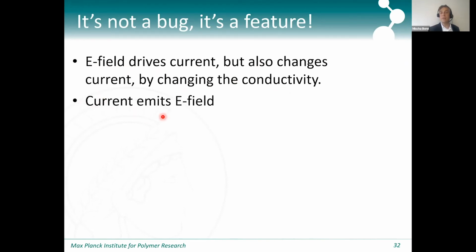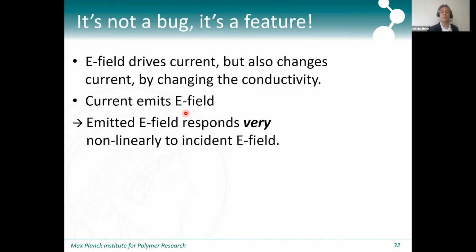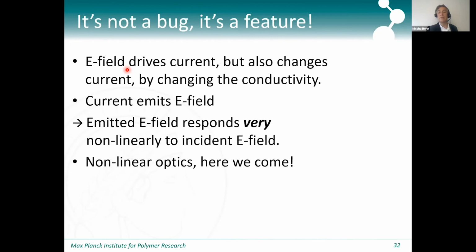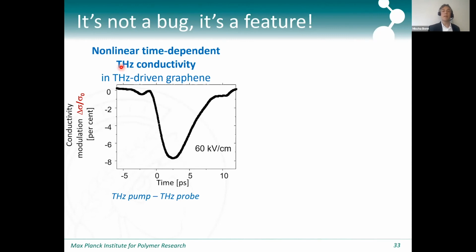We know that the current emits the terahertz field. And so what these two things combined mean is that the emitted field responds very nonlinearly to the incident field. If we increase the incident field strength, we change the nature of the response in a nonlinear way, because the field heats the carriers, and that changes the current because it changes the conductivity. That means this is a highly nonlinear optical material in the terahertz range, and so we should be able to do nonlinear optics with graphene. That's going to be the second part of my talk: using this heating to do nonlinear optics with graphene.